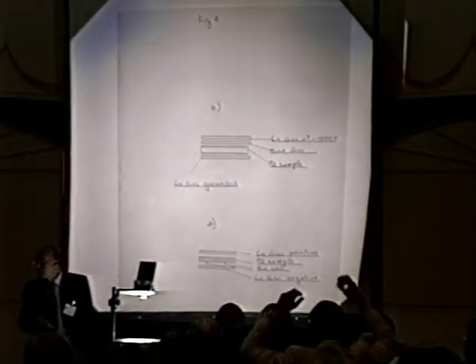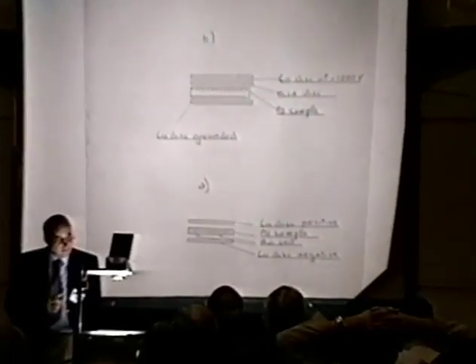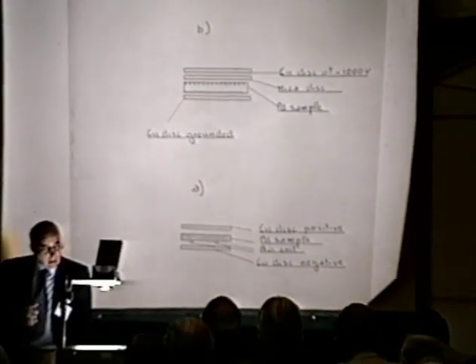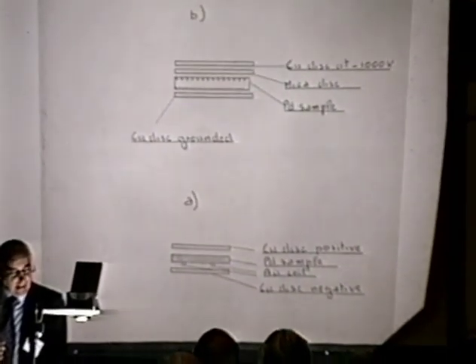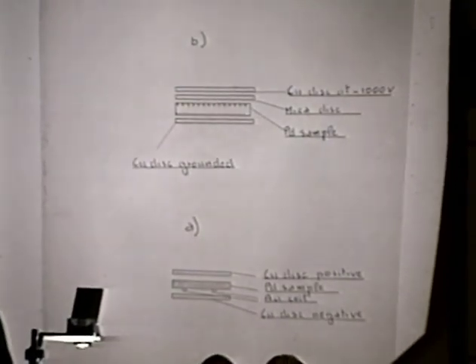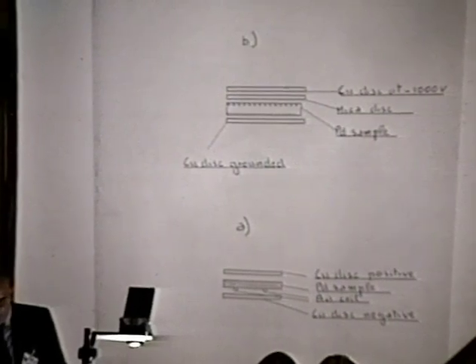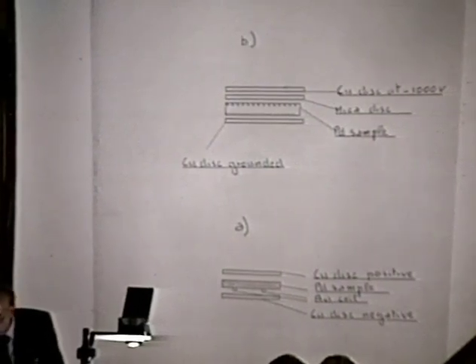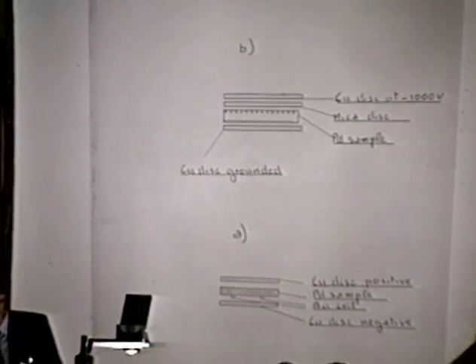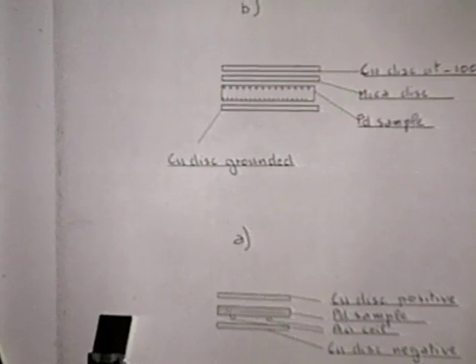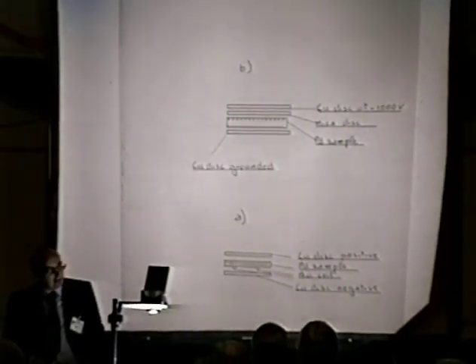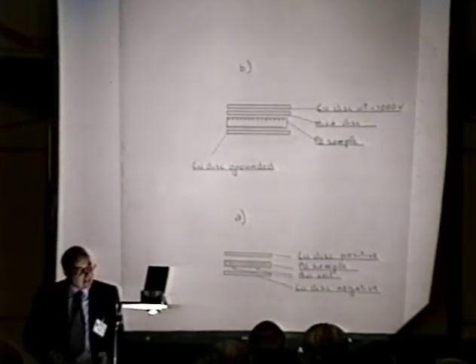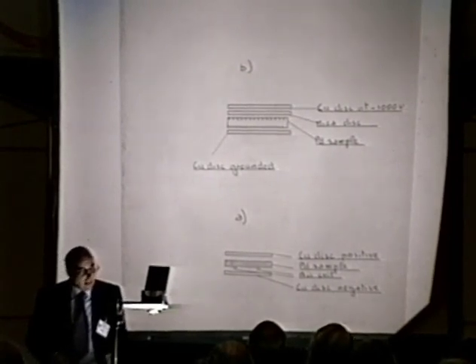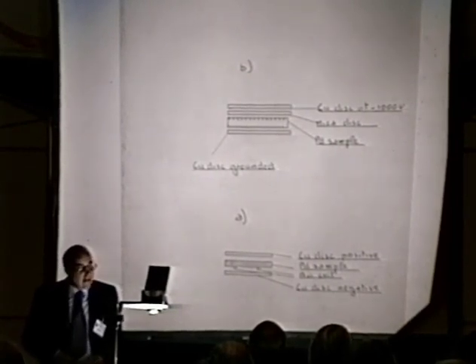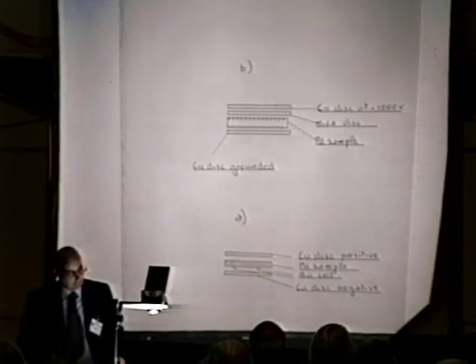We have used this design because it was found that when a palladium sample is submitted to a high field, we have a phenomenon which preliminarily we are calling field-induced overloading, whereby we observe really an increase of the loading ratio.